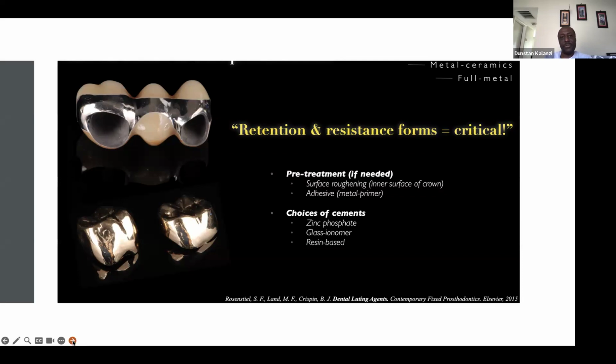Take home for your full metal and metal ceramics. Normally the fitting surface is treated for you in the lab. They'll do surface roughening either using metal primers or sandblasting. And the cements that I would keep are your zinc phosphate, or glass ionomer, or resin based. It's up to you really. If you still have zinc phosphate, it will be good for you. It works beautifully with the PFMs and metal crowns. Just remember to mix it thin. Don't do a thick mix. Do a thin mix that will serve the same purpose.